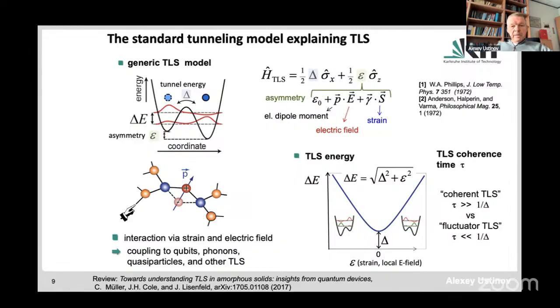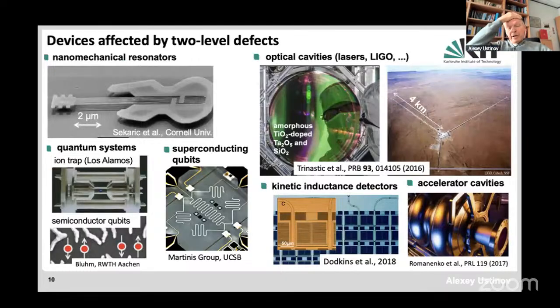So in this talk, I will distinguish between different types of defects. One type, which I would like to call coherent two-level systems, will be two-level systems which have coherence times, let's say T1 of the transition between the lowest energy state and the first excited state, shown by these dashed lines in the sketch at left. I will call them coherent TLS if they form quantum states which live longer than the tunneling time. And then there are the other types of TLS which are also present in the material. I will call them fluctuators. Those will have a lifetime much shorter than the gap, and therefore they will always be incoherent. So in this case, you would not expect any coherent coupling to, let's say, quantum circuits, which we study in experiments.